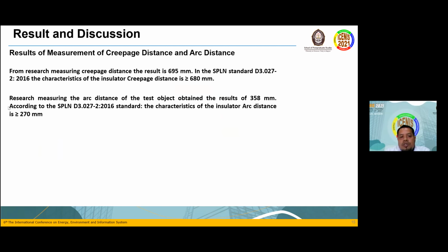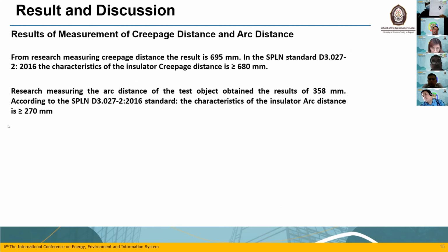Result of measurement of creepage distance and arc distance. From measuring the creepage distance, the result is 695 millimeter. In the SPLN standard, the characteristic of the insulator creepage distance is more than 680 millimeter. Measuring the arc distance of the test object gives a result of 358 millimeter. According to the SPLN standard, the characteristic of the insulator arc distance is more than 270 millimeter.